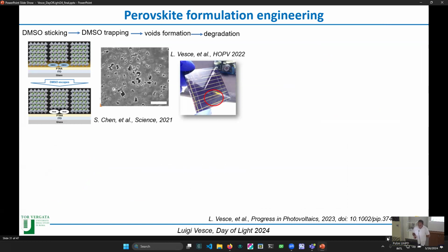We want to fully remove, at our best, the problems that we can have in this process, and we work on the DMSO sticking. The DMSO is one of the solvents that you use when you prepare the perovskite solution. Recently, also from some of our experience in the lab, we face this issue, so that during the perovskite formation, some DMSO can be trapped in between the substrate and the perovskite layer, and then when the DMSO escapes, you have some void formation.